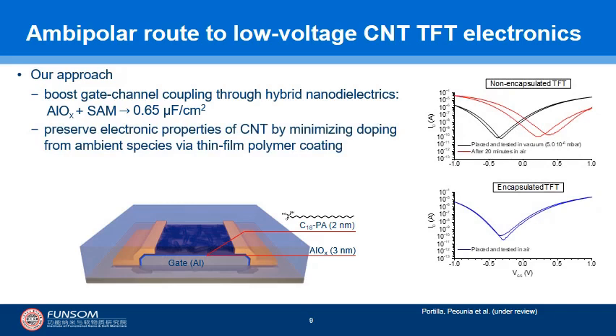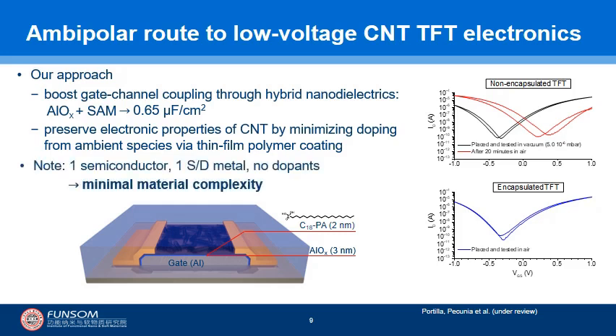Additionally, in order to preserve the ambipolar properties of CNTs, we sought to minimize the doping affected by ambient species. Therefore, we coated our TFTs with a polymer thin film. As you can see from the TFT characteristics shown here, a CNT-TFT without this coating would gradually lose its ambipolar character. By contrast, the TFT coated with the polymer film will still present its inherent ambipolar behavior. Importantly, this approach only features one semiconductor, one source-drain metal, and no dopants. Therefore, it is characterized by minimal material complexity.